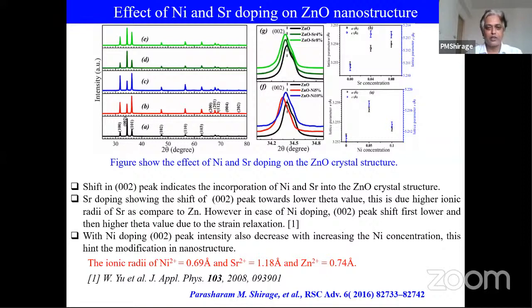And in the case of nickel, it has an ionic radius smaller than zinc. Automatically, the lattice constant will shrink. And that we can easily study by using the X-ray diffraction pattern. The X-ray diffraction pattern will provide important information on whether your material is pure or not. And how to identify whether it is pure or not?